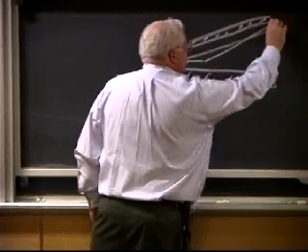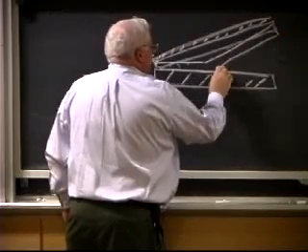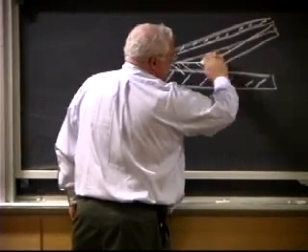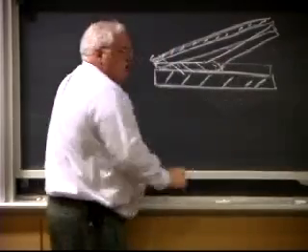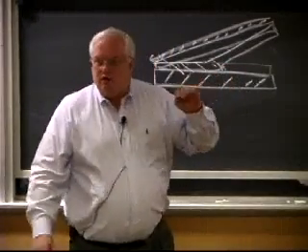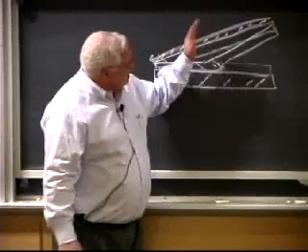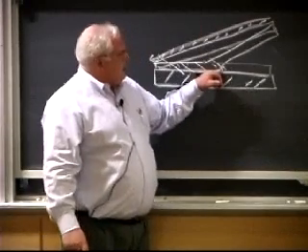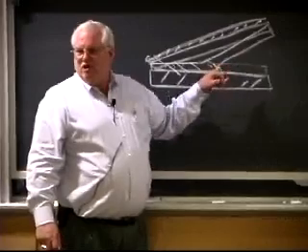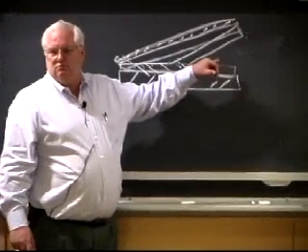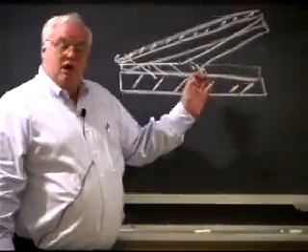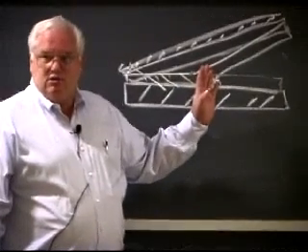If you take high-speed movies, you can actually see that the plate gets slammed against the surface. So this would be in process. Eventually, it slams against the surface, and there's this critical angle. At that critical angle, from the energy of this mechanical impact, you actually get a little jet of your contamination being extruded out of that joint. And you get little waves when you're all done. You actually get very, very good bonds.